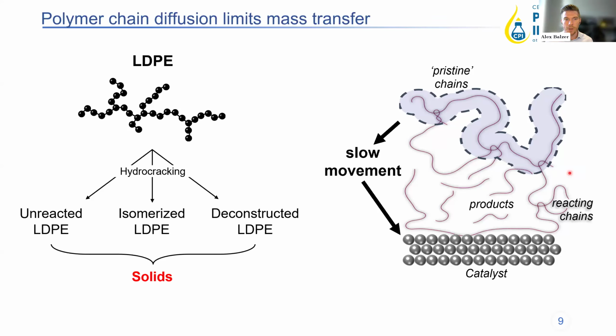And ultimately, polymer chains diffuse on timescales that are tens of thousands of times slower than most small molecules. And so what we're seeing during these reactions is that a chain diffuses to the catalyst surface and has to undergo several chain scission processes until it's a small enough molecule that its diffusion timescale is fast enough to move away from the catalyst before another chain can come in and interact with this catalyst. And that's what gives us this really low molecular weight distribution early on in the reaction time.